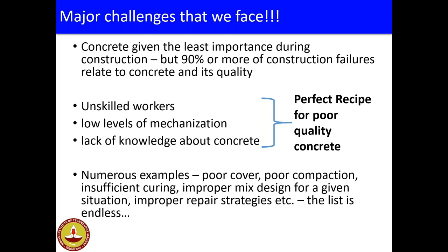Curing is not given importance. If everything goes fine but the compaction is not good, or the curing is not proper, what happens? The quality will decrease. So I've shown here a perfect recipe for poor quality of concrete at site. And not only that, we have improper repair strategies. So many things add on to the deterioration of the concrete. That means we should focus not only on the material part, we should also focus on the process part.